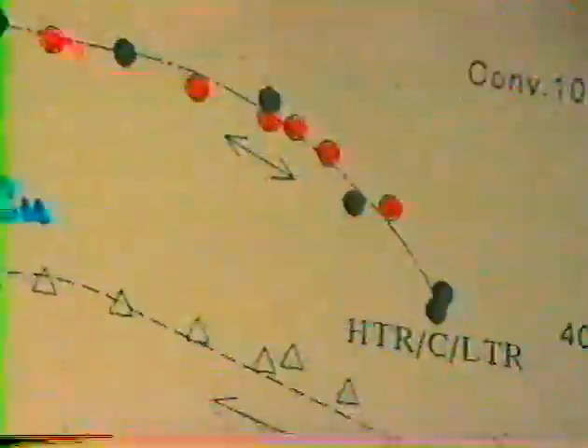We now had an extremely active catalyst flowing under these conditions, 5% CO, 5% oxygen, the balance being helium, at room temperature, or at least at 40 degrees centigrade. That was room temperature in our laboratory that morning. Our air conditioning wasn't working. We achieved, under those conditions, 40% conversion of carbon monoxide at 40 degrees centigrade.